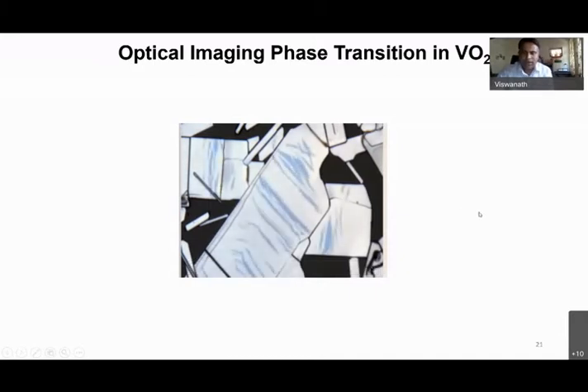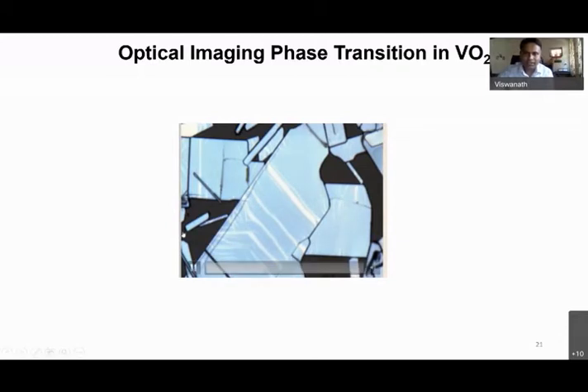So this is recorded using the optical microscope during heating. Whatever color change you see here, let me repeat: initially it is a white color. You can see small lines, like stripes, essentially of gray color. That essentially corresponds to the metallic phase. Again, there are some papers on why there is an optical color contrast. As I said earlier, the optical properties also change during the phase transformation.